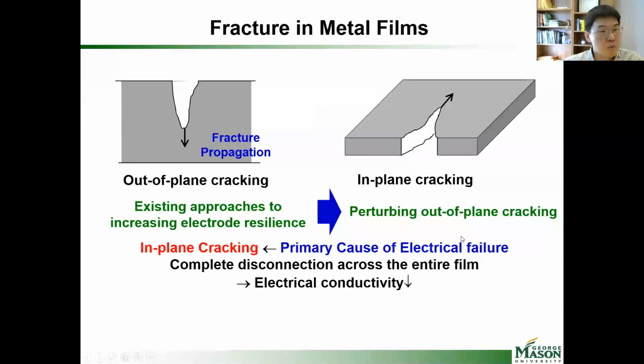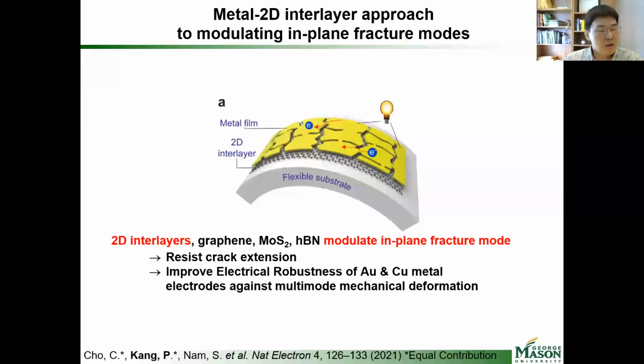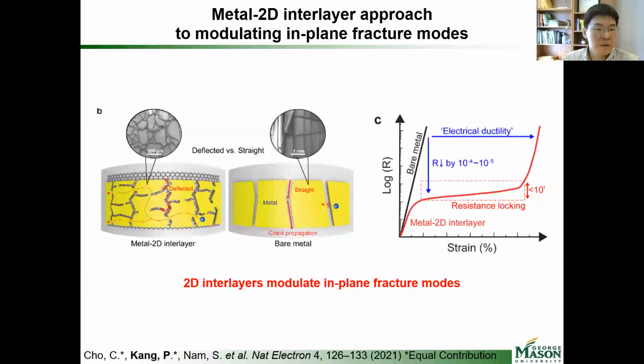And just to give you a sense of what we do, even with the atomically thin materials, we can modulate the fracture modes. And here, in collaboration with other groups at the University of Illinois, we explored that using these atomically thin materials, we can even modulate the fracture mode of metal films. These metal films are widely used for biomedical applications, for example, like multi-electrodes. So it can be used for implantable electrodes. But here, using atomically thin materials, we can modulate the fracture mode.